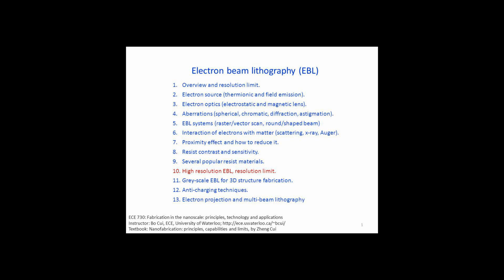The drawback to using low-energy electrons is that it is hard to prevent spreading of the electron beam in the resist. Low-energy electron optical systems are also hard to design for high resolution. Coulomb electron repulsion always becomes more severe for lower electron energy. Another alternative in electron beam lithography is to use extremely high electron energies, at least 100 keV, to essentially drill or sputter the material. This phenomenon has been observed frequently in transmission electron microscopy.